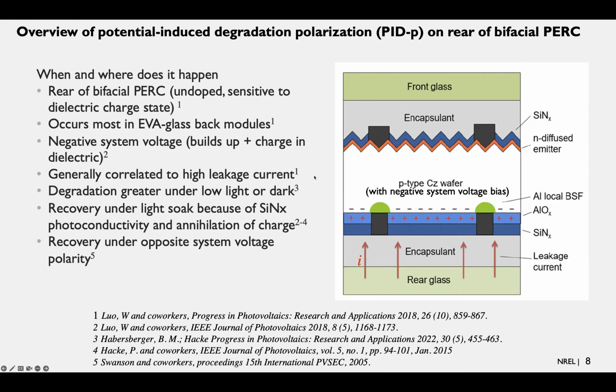It builds up positive charge in the dielectric, as I went through just a minute ago. It's generally correlated to higher leakage current, whereby leakage current goes through the glass and encapsulant. And the degradation is greater under low light or in the dark. On the other hand, a recovery occurs under light soak. The whole reason for this light sensitivity is because silicon nitride is photoconductive, and that photoconductivity can lead to annihilation of charge, reducing the amount of buildup and reducing the amount of PID polarization.